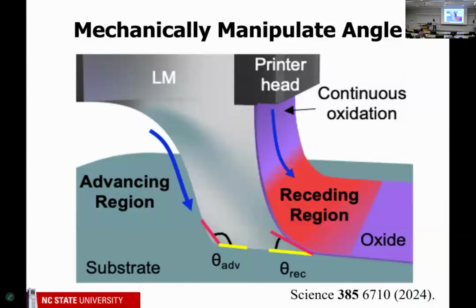Which is to take the liquid metal and essentially drag it across the surface. So what we do is we put the liquid metal, we call it a printer head. That's a very fancy word for saying 2 glass slides that are like this. And we put the liquid metal between it. And this is not quite to scale. There's a small gap, maybe 500 microns, where we drag it.